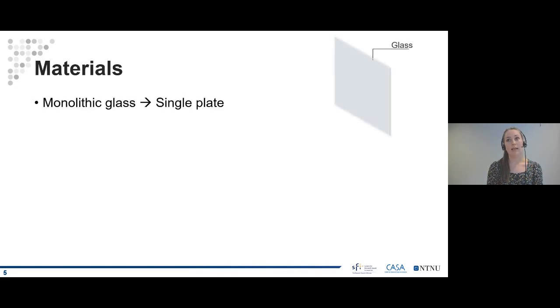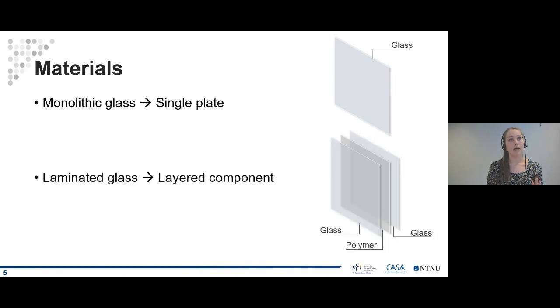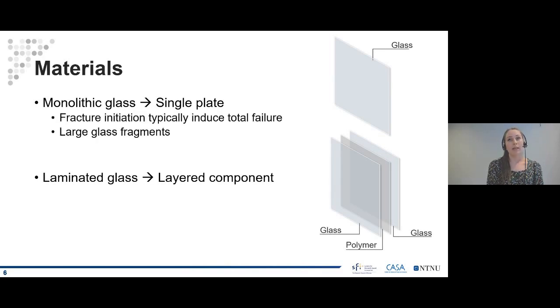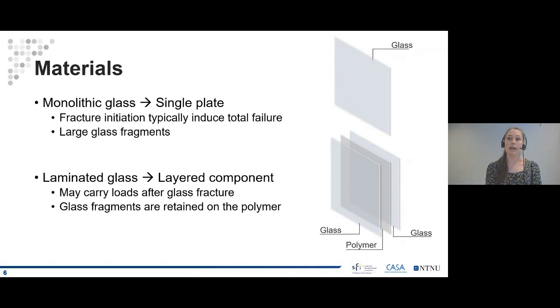The types of glass that we studied during my PhD were monolithic glass, which is a single plate of glass, and also laminated glass. Laminated glass is a layered component that consists of at least two glass plates and a polymer interlayer. These layers are bonded together through a process that includes heat and pressure. For monolithic glass, fracture initiation will typically induce total failure of the entire plate, and it will also create large glass fragments. Laminated glass can still carry loads after the glass has fractured, because the glass fragments will be attached to the polymer interlayer.